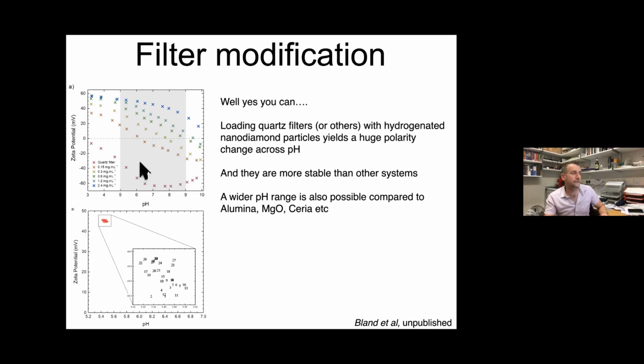We've looked at a few that I've got on the bench from CMP, like alumina, MgO and ceria, and they tend to be more around 20 to 30 millivolts, which means it's way weaker. Also their pH range is way smaller. So it's not actually that useful if you want to pull these things out of water. So we load them onto the filter, we react them, and they're super stable.